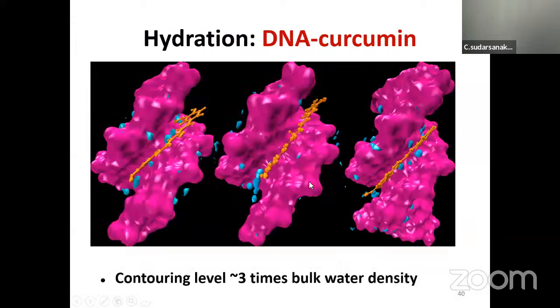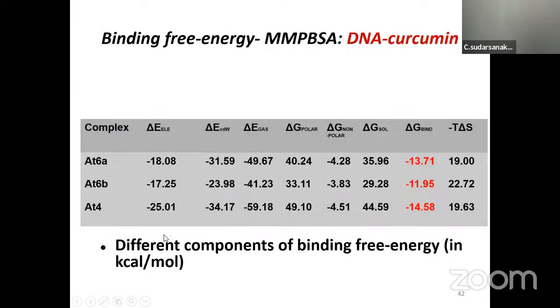So this is what you find, similar to crystallography, contouring the electron density. When you calculate, you find that this is the minor groove where this one sits. One is an AT-rich sequence, another one is an AT sequence, and this is the GC sequence. In all these cases, binding is quite favorable. Now you can calculate the binding free energy, the energetics of the binding. You can have all these parameters. Finally, what we get is the delta G, the change in free energy due to the binding.